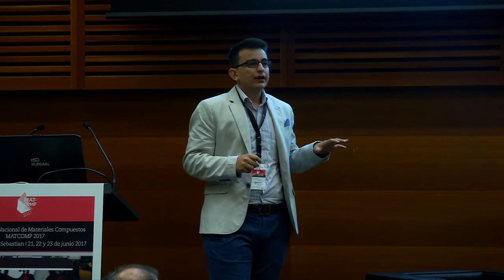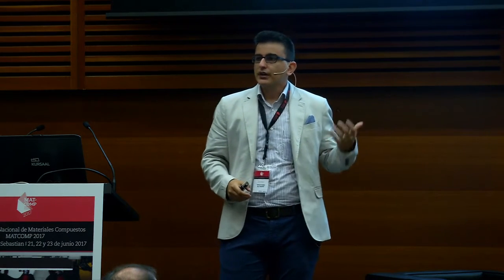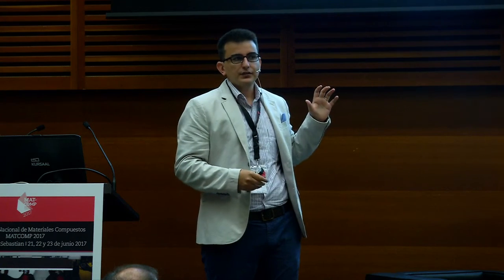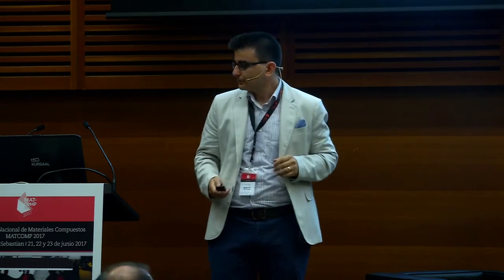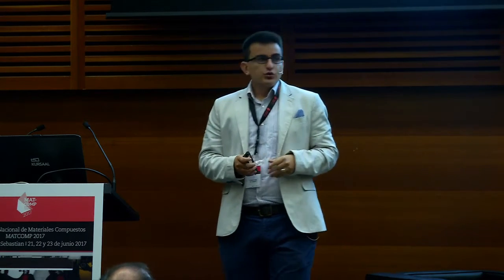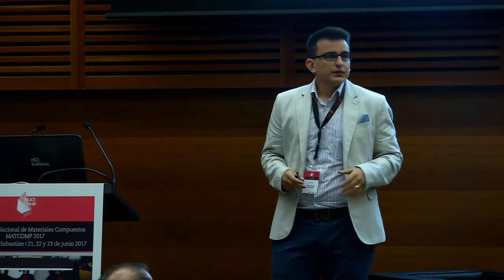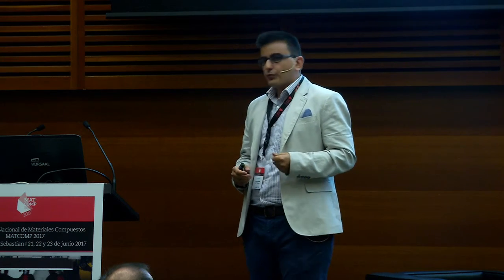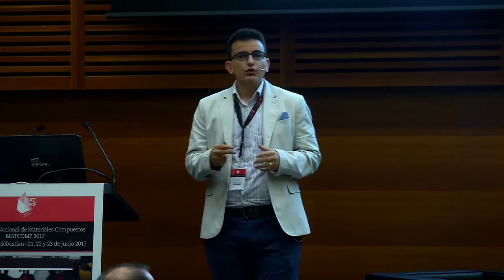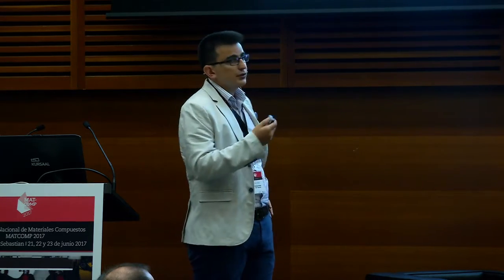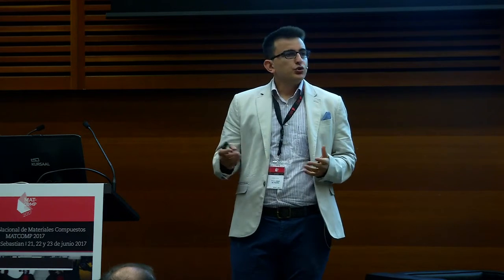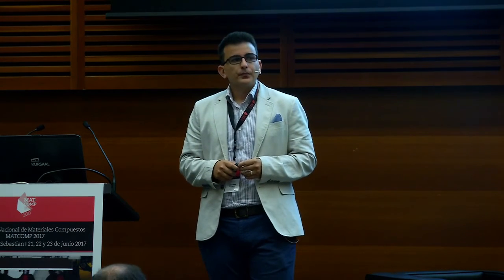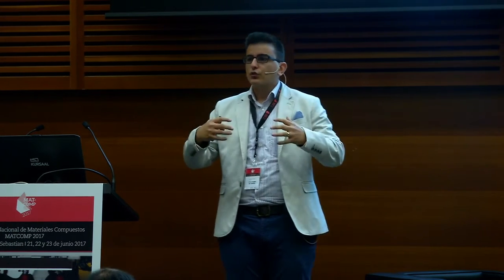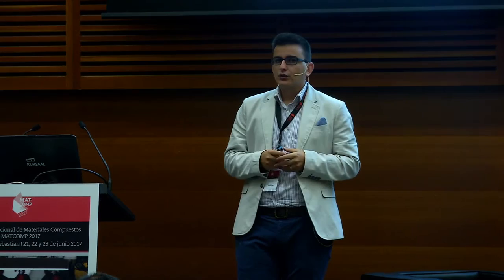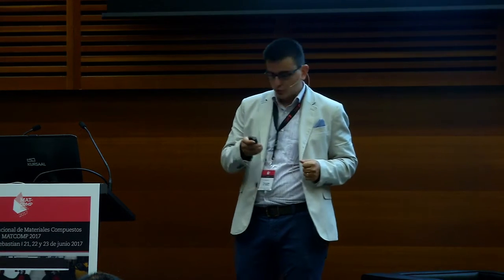So in order to have, again, a reliable manufacturing of composites, we need to understand, describe, and predict these kinds of physical phenomena during the process. So usually we start with material characterization. It's obvious that with the current state of the art, we can predict and analyze the chemorheology, thermokinetics, and thermomechanical properties evolving during the process. And here I have an example: cure kinetics, temperature and cure dependent elastic modulus, and the viscosity. So the idea is transferring all this data to numerical process simulations to predict the physical phenomena taking place during the process.